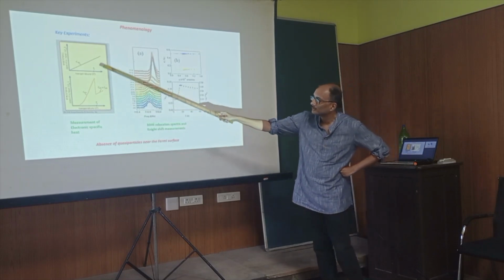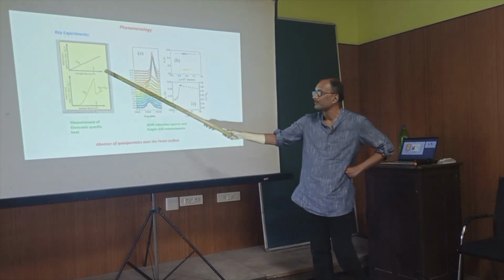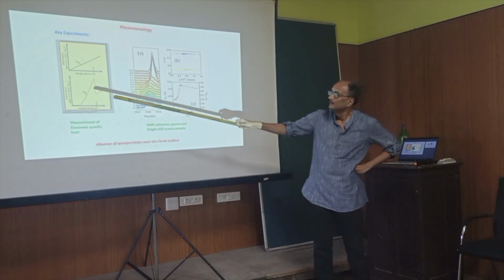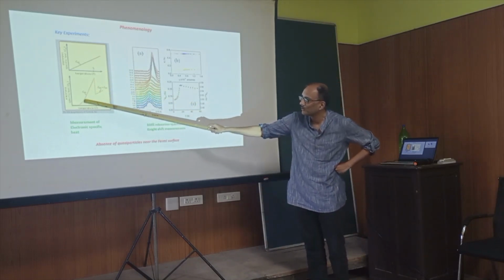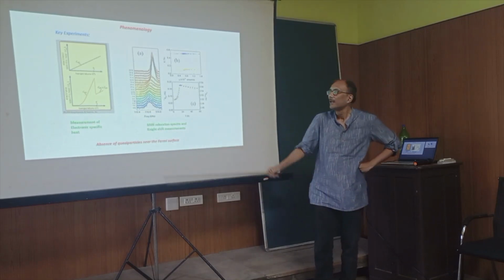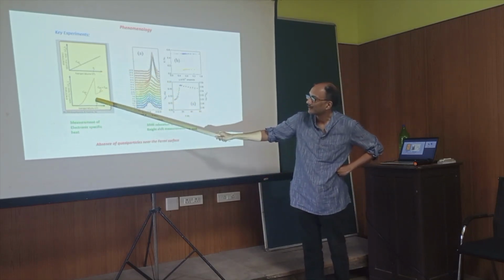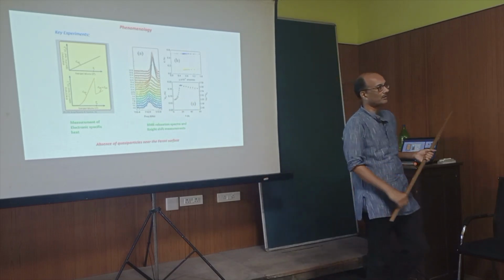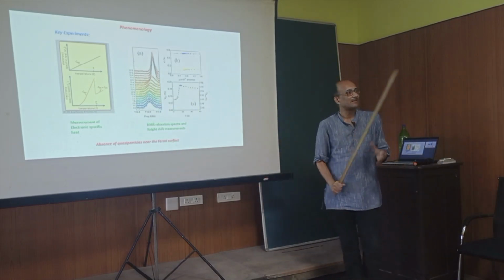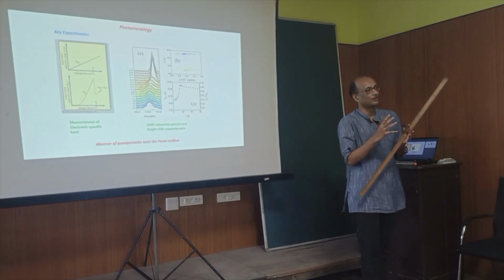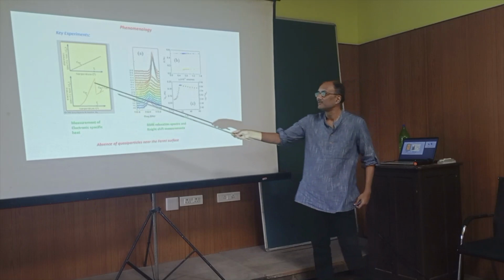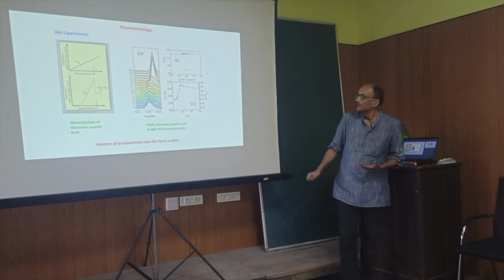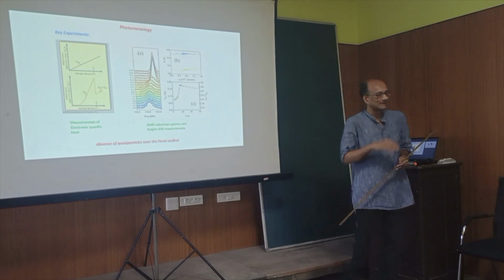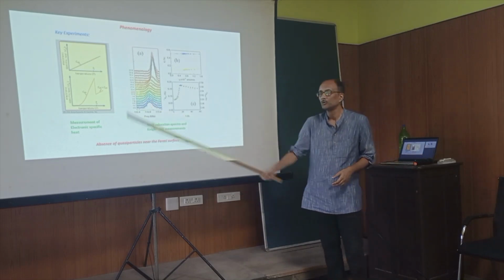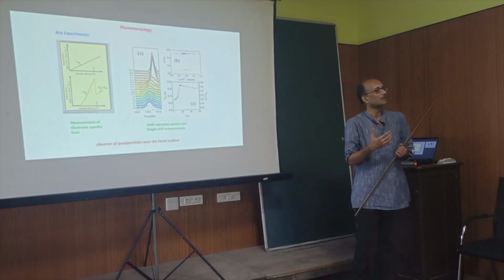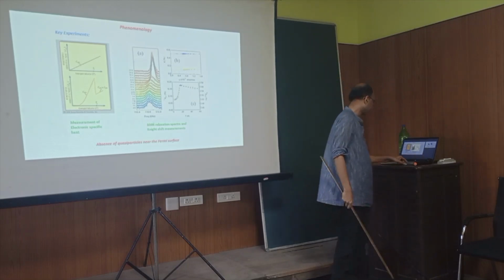So in metals, since there are a lot of available electrons, this linear behavior is easily seen. However, it seems that when you cool the temperature and this metal goes into a superconducting state, this contribution goes to zero almost exponentially. Okay? And there is a sudden jump at the critical temperature at which the sample goes to a superconducting state. So this tells you that something fundamentally different is happening with the electrons inside the materials, and that is being reflected in the specific heat. So these are all experiments until the 1950s which gave crucial clues to the fact that superconductors can be a really different state of matter.